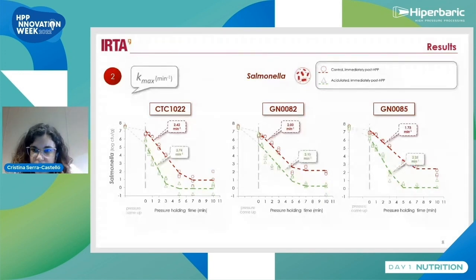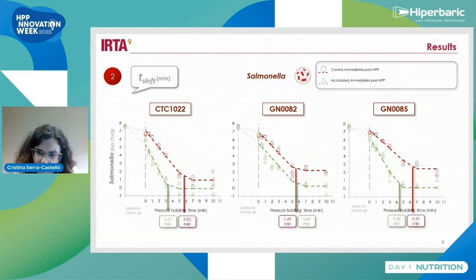If we look at the Kmax, we can see the inactivation rate of Salmonella is systematically higher in acidulated products compared to control. However, the other parameter that the log-logistic with tail model gives us, the T-shift, we can see the appearance of a resistant tail. What does it mean from the technological point of view, the appearance of this resistant tail? It means that whenever you increase the pressure holding time, no further inactivation of Salmonella will be achieved. So this is a technological parameter important to be taken into account when defining the process parameters of our own process.